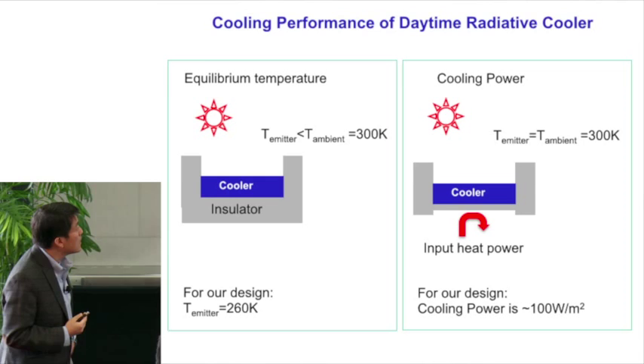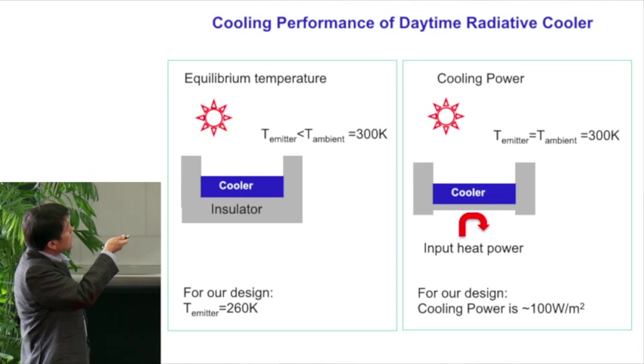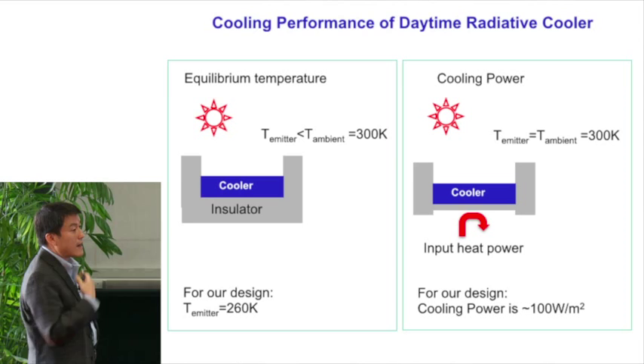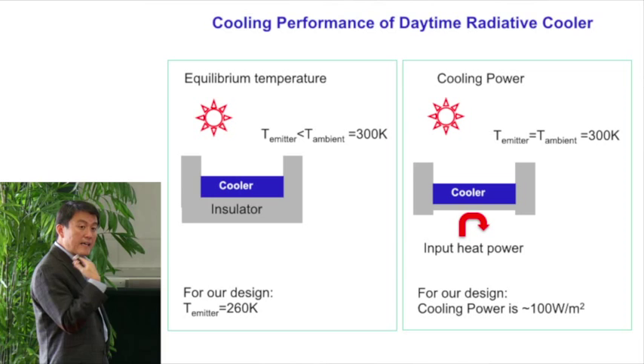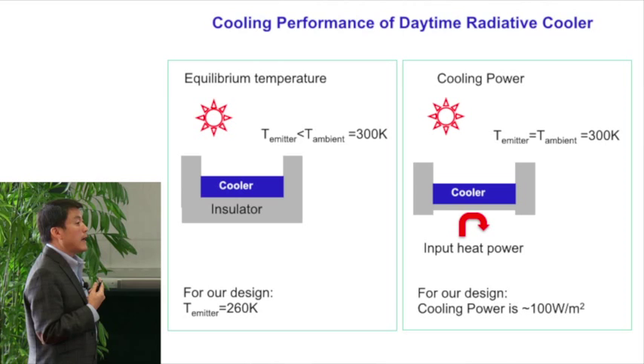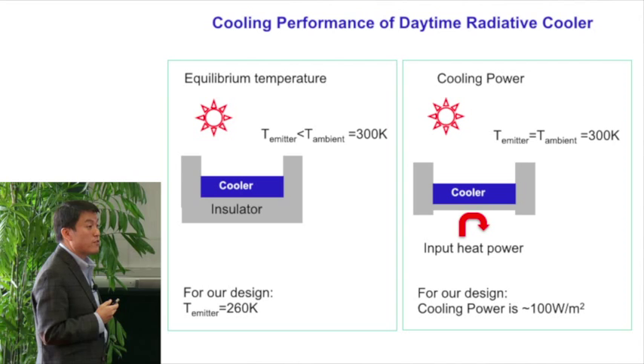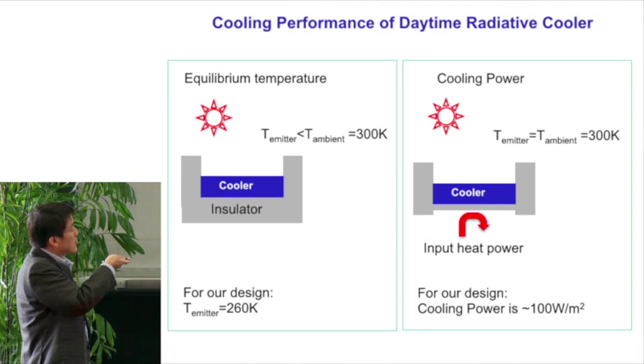One measure of it is something called the equilibrium temperature. Suppose you have this thing on a roof, with a perfect insulator surrounding it, but with sky access. In this case, it reflects all the sunlight, so it doesn't get heated up by the sun, but it radiates the heat out, so its temperature is going to drop. You can ask, for a given ambient air temperature, what temperature is this cooling device going to reach? Using the spectra I just showed you, theoretically, you could get a temperature of about 260 Kelvin for an ambient of 300 Kelvin.